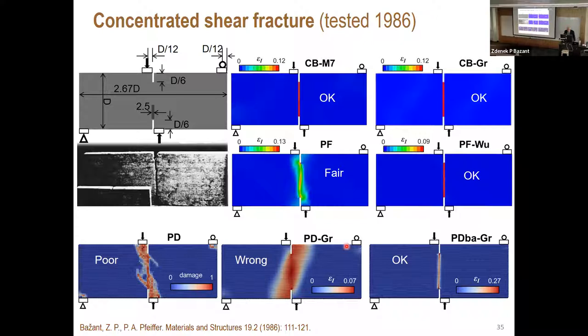Now, another interesting and I think important test which has been totally overlooked, we tested in Northwestern 1986 concentrated shear fracture. It's a 4-point loading, and normally you put these loads farther away from the notches, and then you get two cracks diverging apart, curved mode one. But if you put the notch close, then you produce perfect mode two crack. Why? Because the zone of very high strain energy is very narrow. So you reproduce it perfectly with crack band model M7, also Grassel, with phase field, not too well, actually should not go here. With phase field Wu, actually you do it quite well. For Peridynamics Grassel, you get completely wrong. So, for bond associated, you get it reasonably well, you get it good.